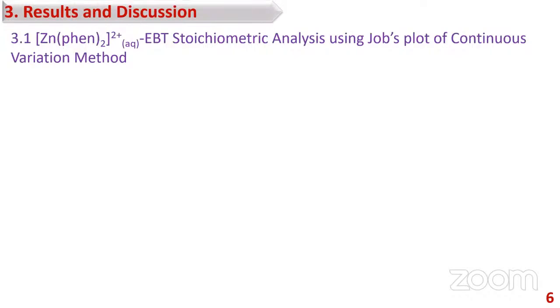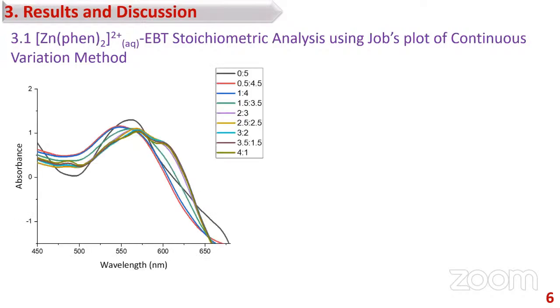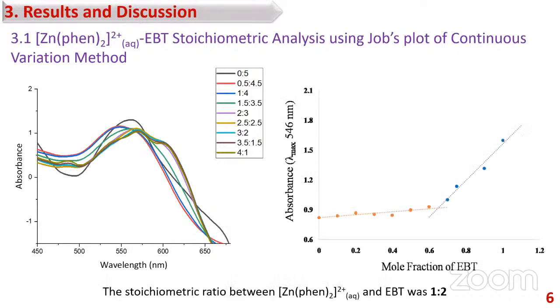Let's turn to the results and discussion part. Here, in order to find out the stoichiometric ratio between the zinc phenanthroline complex and EBT, the Job's plot of continuous variation method was used. Here, a series of solutions were prepared and the UV-visible spectra were recorded and illustrated as shown in the graph. The absorbance data at 546 nanometer were extracted from this graph to draw the Job's plot as shown here. From this plot, the obtained stoichiometric ratio between the zinc phenanthroline and EBT was 1:2. Along with the optimum pH of 10, this stoichiometric ratio was maintained throughout the whole experiment.